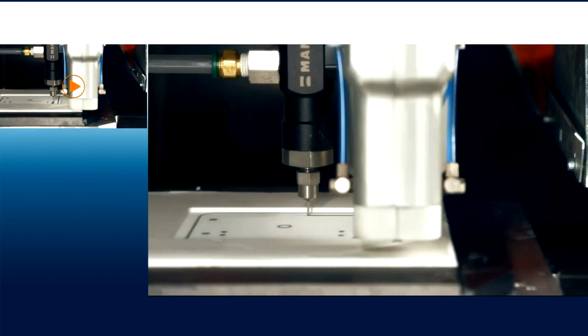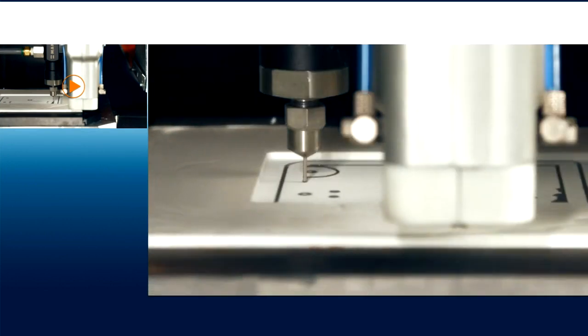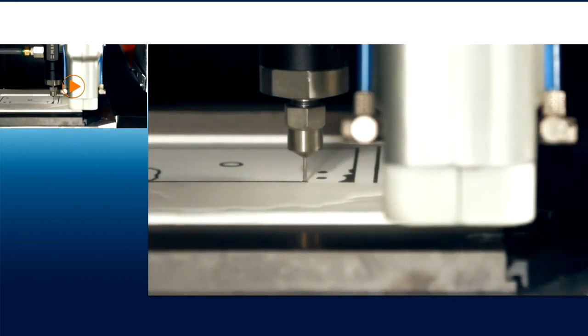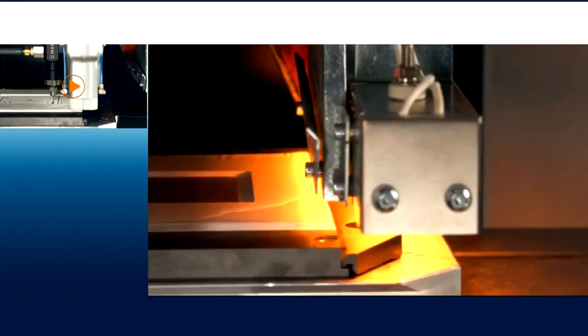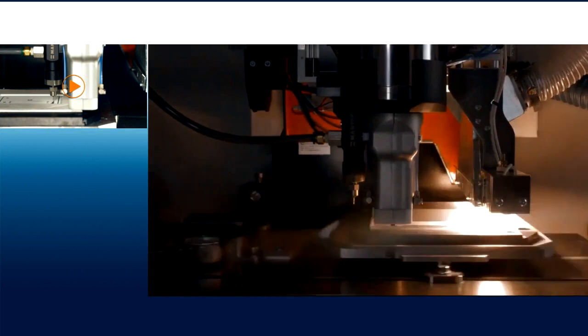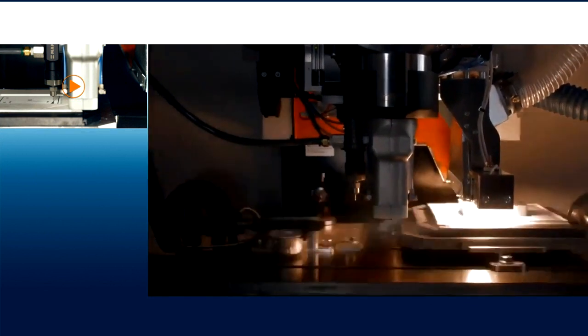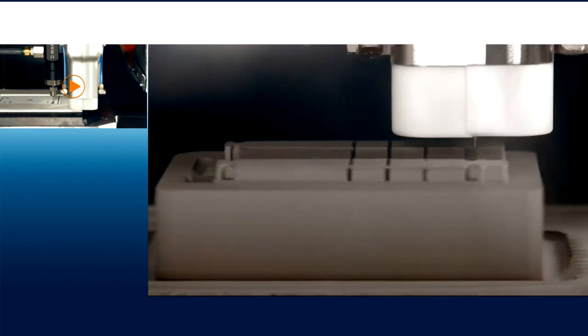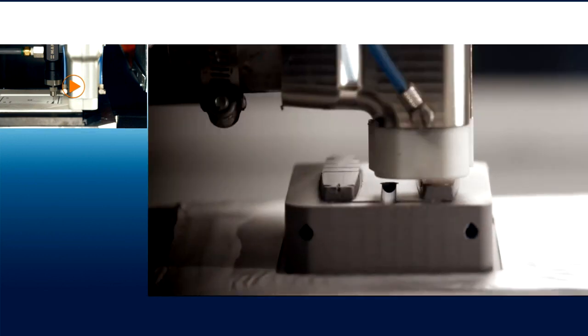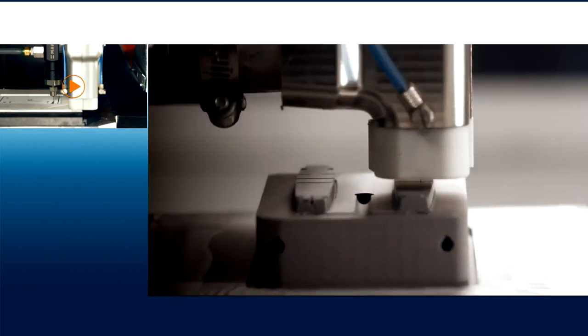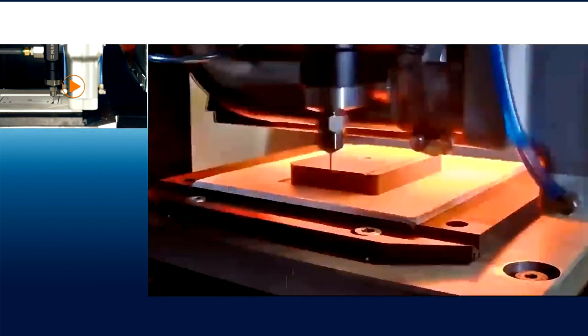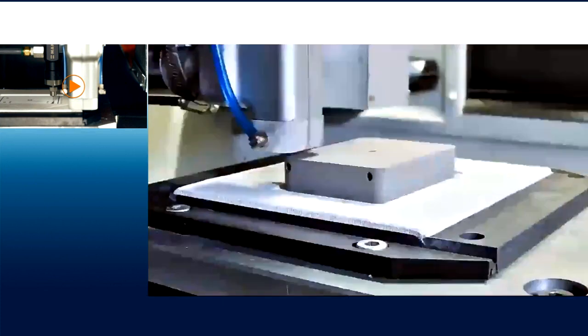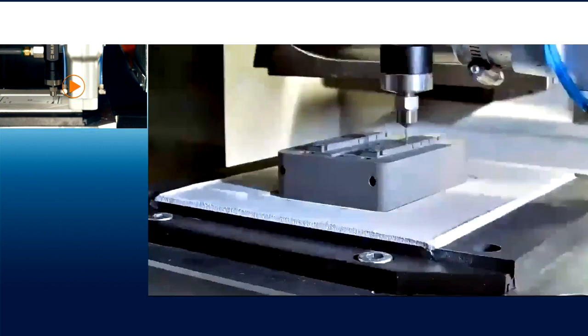You'll see it starting by just simply extruding that paste material. It's not even being heated, it's viscous enough to just extrude it out, print a layer, go through and dry that layer. So that's removing that solvent out. It's firming it up so it's firm enough to be machined. And then it goes ahead and is machined. We're using standard cutting tools here. Our smallest tool actually is a 6 thou ball end mill. So some really, really small cutting tools. You can see the shapes are refined, improve the surface finish, add features that couldn't have been printed. This is going to repeat over and over and over again to build up the part.